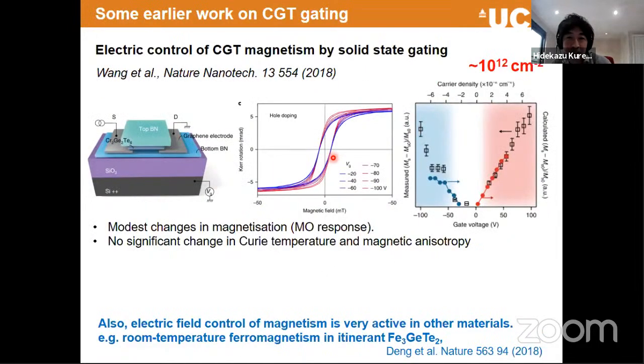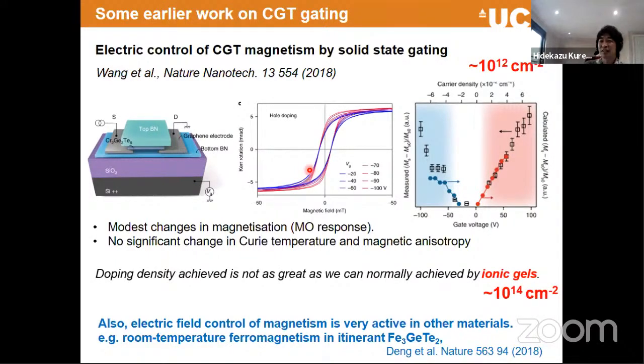Here, for example, it's probably easy to say if this effect is a linear response. It's probably very crude to say, but we can just increase the carrier density 10 times, 100 times more. So that means that if this effect is linear in n, then our effect is 100 times bigger. This is a very, very crude way of putting it. Just the more electrons, the stronger the effect and the stronger the impact on J.